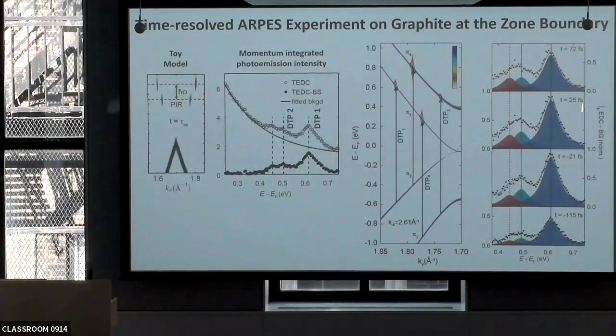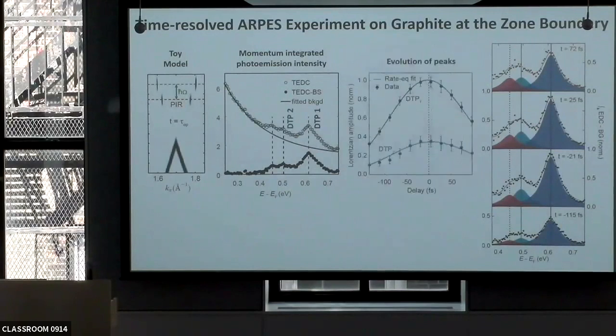And what you see here as a function of time is a change in delay. So here is as the pulse is coming in, and then the 2 pulses are coming closer and closer together. And the system evolves, and you see how the intensity grows and then decays again. So what we can do next is really follow as a function of time the intensity of a primary peak, let's say the 2 electronic peaks, so DTP1, where DTP stands for direct population. What you can see is they have a maximum which is close to the 0 delay, meaning pump and probe overlapping exactly, and then it comes up to it and down from it with a width which relates to the width of the pulse.